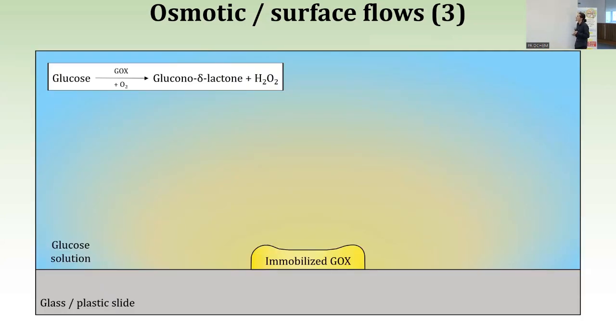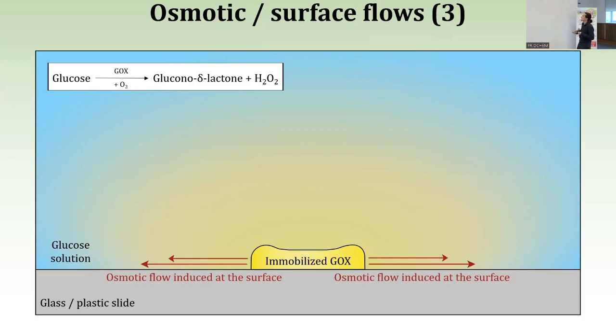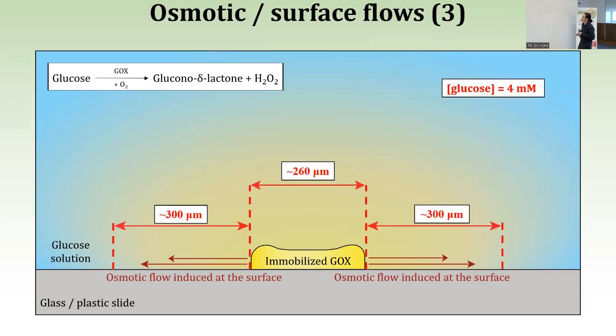Now, again, the schematic explanation. This time the glucose oxidase micropump in a solution of glucose produces these osmotic flows at the surface that push away the tracer particles. For, let's say, a 260 micron diameter glucose oxidase micropump, we obtain a depletion zone of about 300 microns.